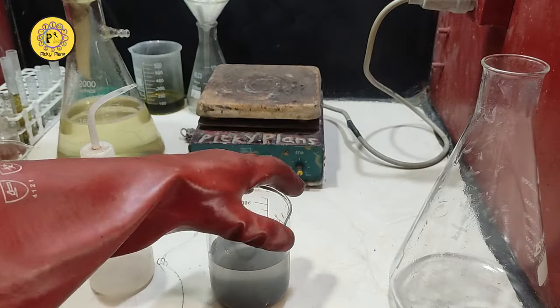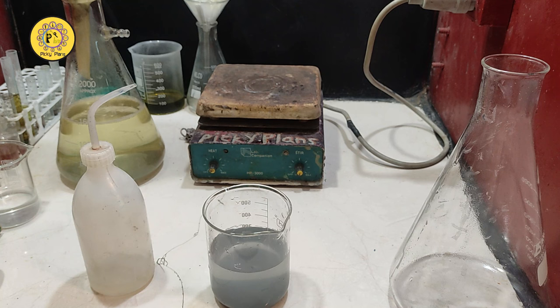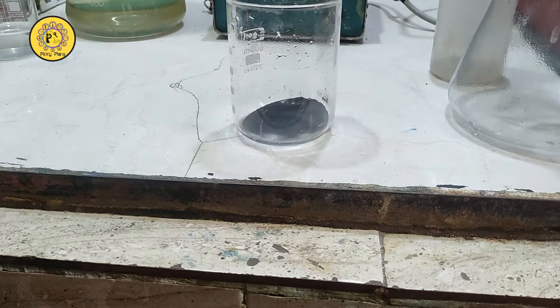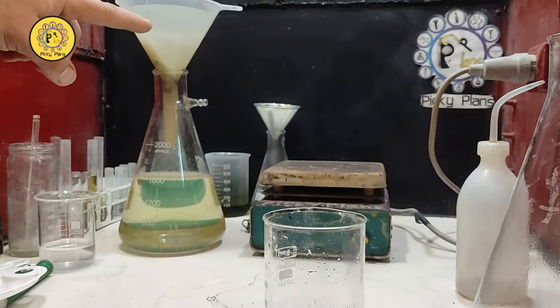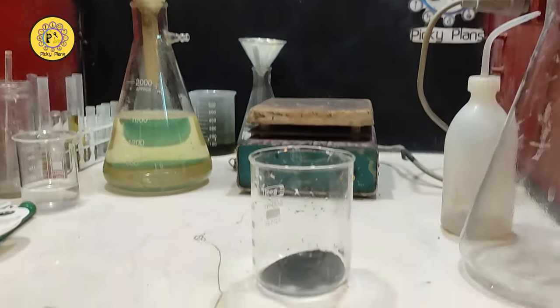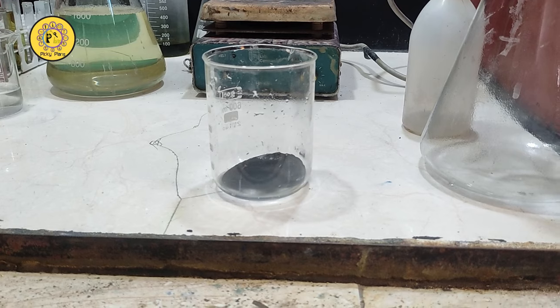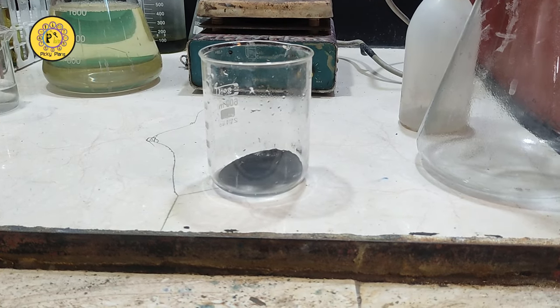I need to let this settle down for a while and then pour off the excess water and start adding the hydrochloric acid to release the gold. Alright, the zinc powder is being washed with water, and I've also added water to the funnel to catch any possible zinc particles. Now it's ready to add hydrochloric acid to start the reaction.